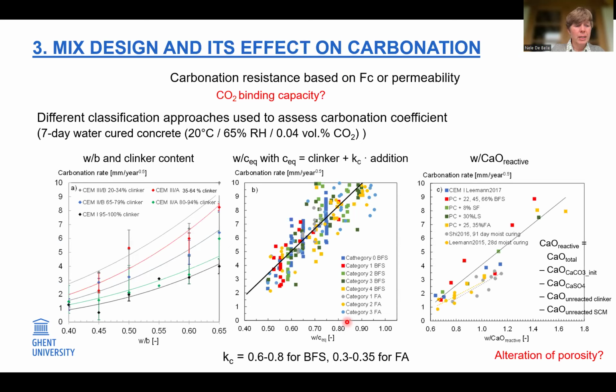Now, how can we estimate carbonation resistance of a certain mix? In the past, this was often done just based on compressive strength or permeability. However, this is ignoring the CO2 binding capacity. To overcome this, in a first approach, the carbonation rate can be related to the clinker content and the water binder ratio. This is quite simple to apply, but it neglects the buffering capacity of the specific type of SCM and the alteration in the pore size.